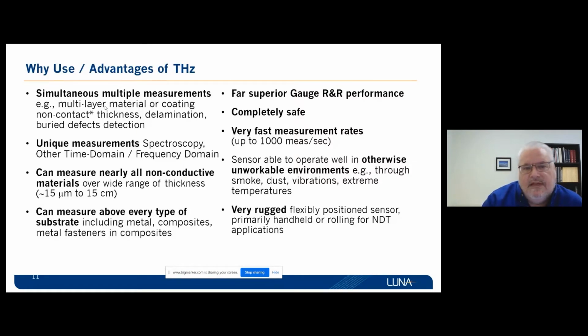So some of the advantages here is that you can measure multi-layer materials. It's non-contact. You can look for things like voids, bubbles, delaminations, buried defects. You can measure the thickness of wet coatings. Okay? So you don't have to contact them yet. You can measure them as they dry. You can predict wet to dry thickness. And you can also do both spectroscopy and frequency domain measurements if you like.